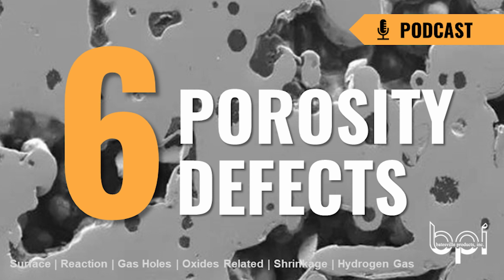So the next one we'll talk about here would be the reaction porosity. And I think we actually had a quick conversation before we got on, and that's when Brad hopped in, and Brad called it what? Reaction porosity, absolutely. And the reason, Monty said, you have to dry it. If you put a mold coating on and you cast that wet, there's going to be a reaction between the molten aluminum and the mold surface. It'll be just very close to the mold or to the core surface. You won't see the porosity typically anywhere else in the part or adjacent to the part. If you have a round core, it'll often show up as a pattern of holes all kind of outlying the core, but very much surface related.